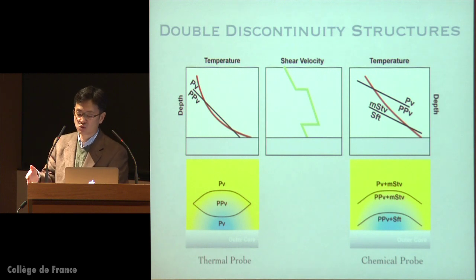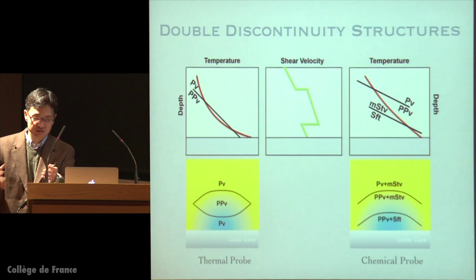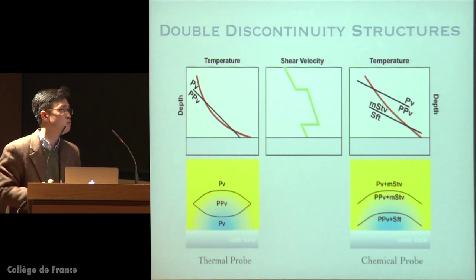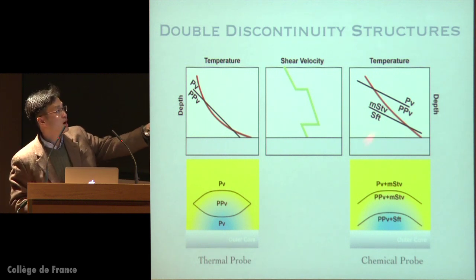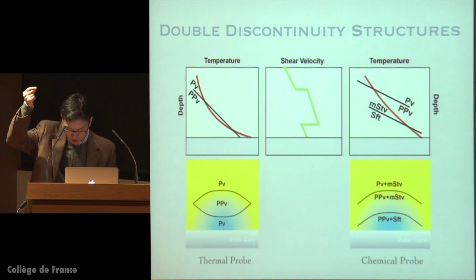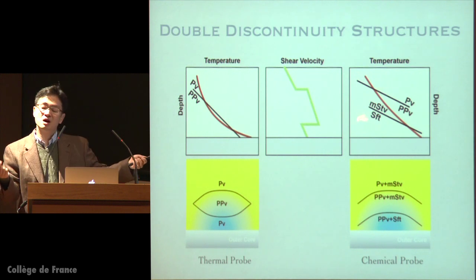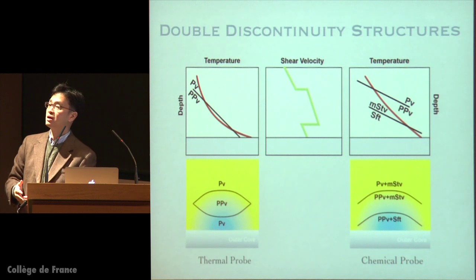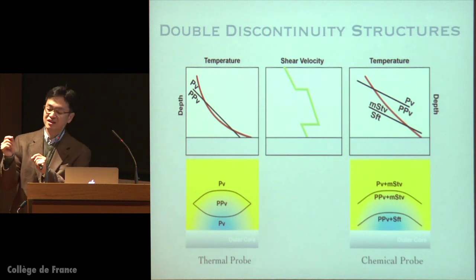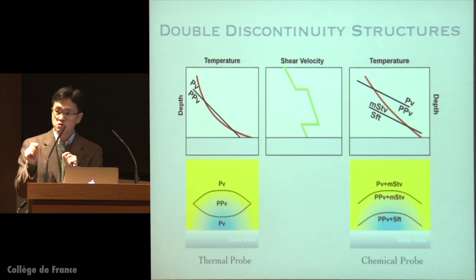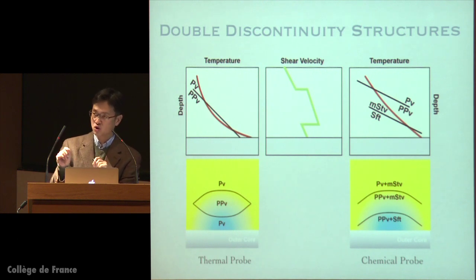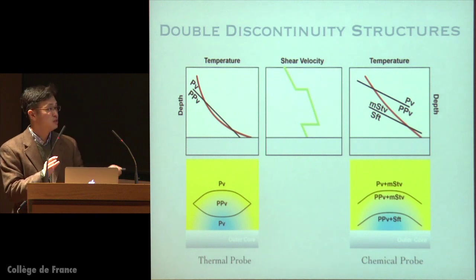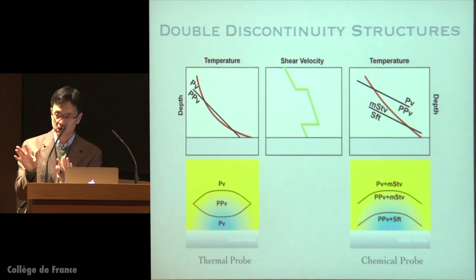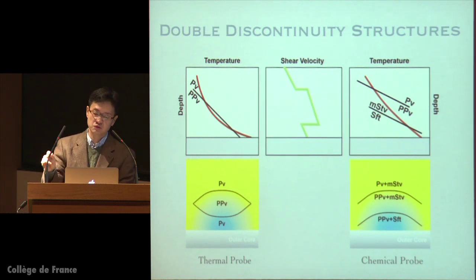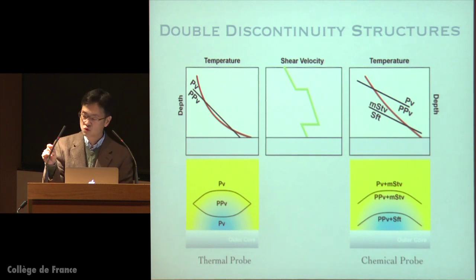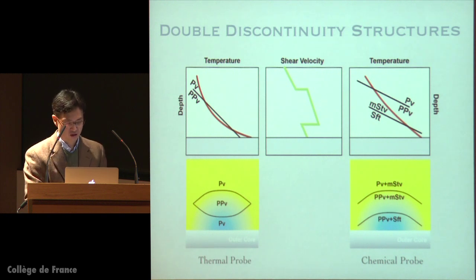Instead, if you have silica-rich material, and if you happen to have both post-perovskite transformation and silica transformation in the same region, what you can hypothesize is that you're crossing the boundary twice through the geotherm, and because their Clapeyron slopes are nearly similar to each other and positive, you would expect to have positive correlation between these two boundaries. What that gives you is that the double crossing idea would remain as a very interesting probe for the temperature in the lowermost mantle. If this scenario is applicable for some of the observations, I don't know whether it exists or not, then it could potentially give seismologists a chemical probe to trace where the recycled materials may end up being in the core mantle boundary.